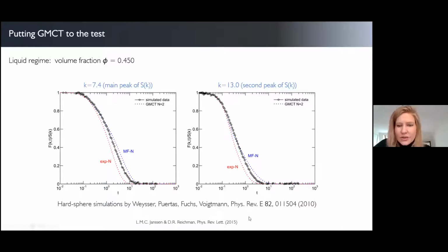These are actually fairly old results from 2015, but I think they still show nicely what the theory can and cannot do. So here I'm showing you some results for the microscopic dynamics of a glass forming system of hard spheres simulated by these authors here. So they provided us with the static structure factors at different densities, and they also provided us with the real intermediate scattering functions coming out of the simulations. And that's what you see in black here. So these are the real exact dynamics from simulation. And I'm showing you plots for two different wave vectors here, left and right. The blue curves here are the mean field closures, and red is an exponential closure.